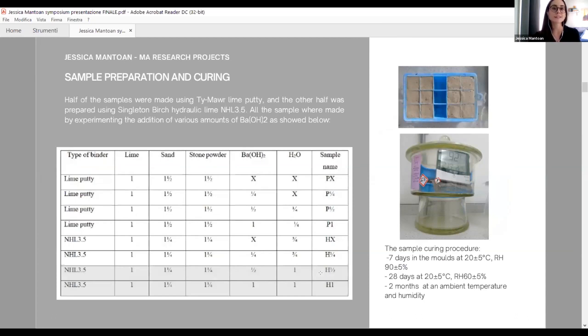For the preparation of the samples, I decided to make two groups of mortars: one with non-hydraulic mortar, using a commercial putty, and the other made with natural hydraulic lime 3.5. From my research with some conservators, I realized that this one was one of the most commonly used in conservation works in situ for monuments and architectural elements.